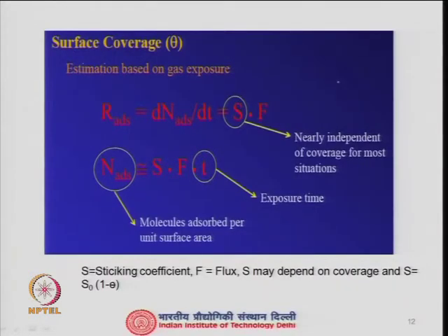Here right now I am talking just about characterization, not the chemical reaction like what I have shown before. The rate of adsorption, you know, is nothing but dN/dt, the number of molecules adsorbed on the surface, and that is related to a sticking coefficient S times the flux F. We have already seen the calculation for F, which is nothing but 1 upon the square root of 2 pi m k_B T, times P.